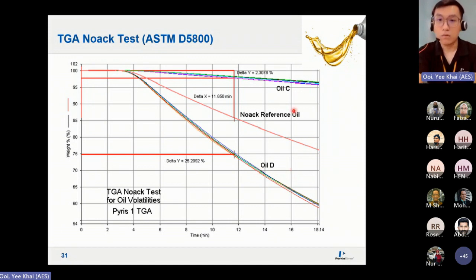Comparatively, you can see from here that for the oil that you manufactured, at the same time that you sample for the weight loss, the loss must be smaller than the reference oil. So in this case, oil C has lower volatility compared to oil D. Oil D definitely fails, because its oil loss is much higher compared to the reference oil at the same time duration.